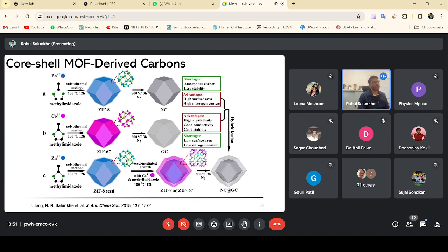In another approach, now we have an amorphous carbon. So if we consider zinc ions and 2-methylimidazole, we can get a ZIF-8 network. The advantages with this kind of carbon are that it has a very high surface area, over 1500 square meters per gram, and it has a very high nitrogen content. Whereas the disadvantage is its very amorphous nature, and it has less stability. These are the advantages and disadvantages associated with this kind of carbon.